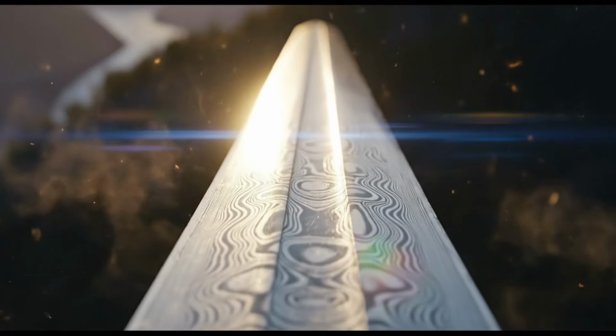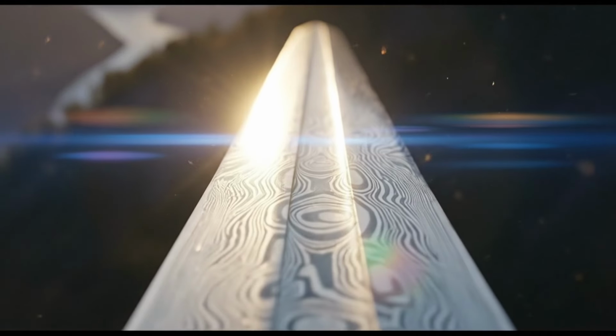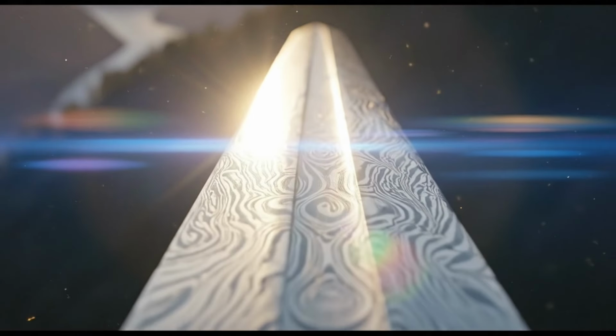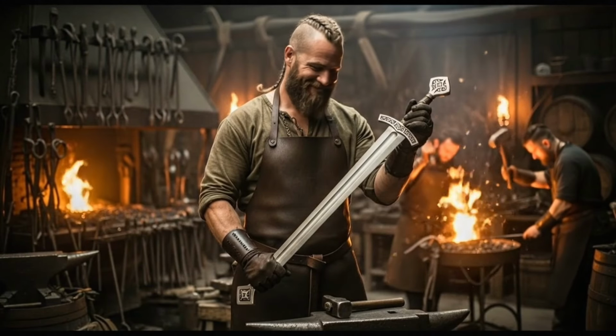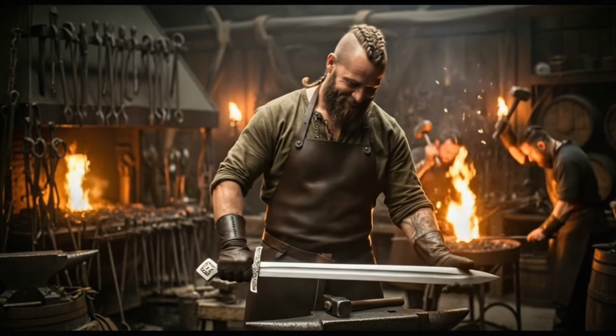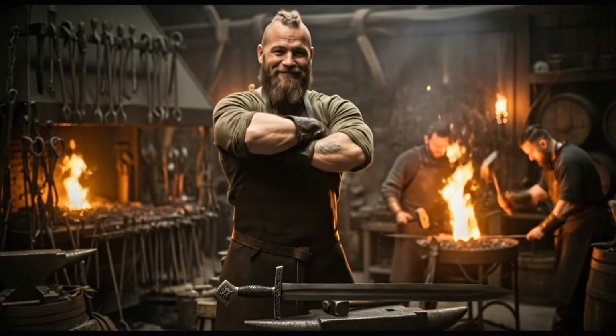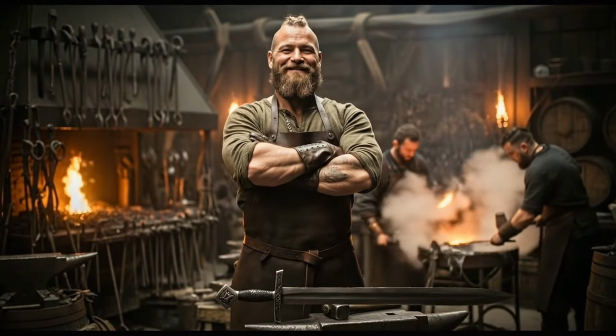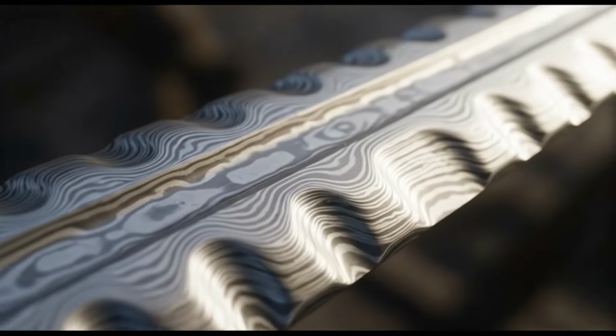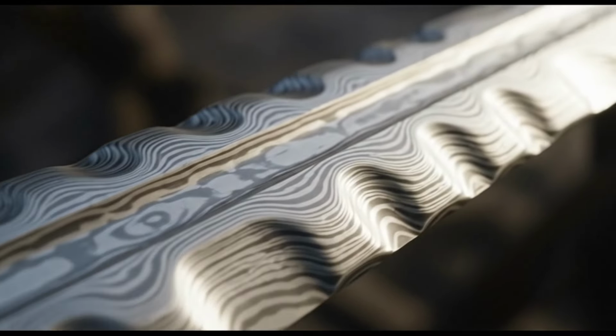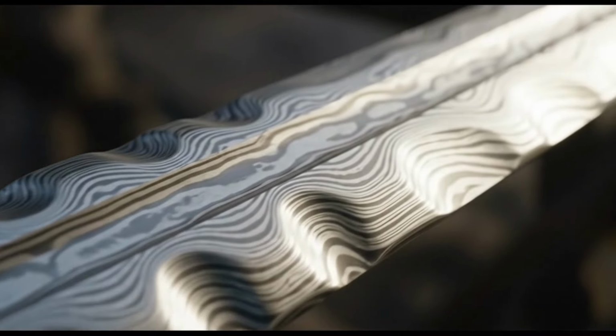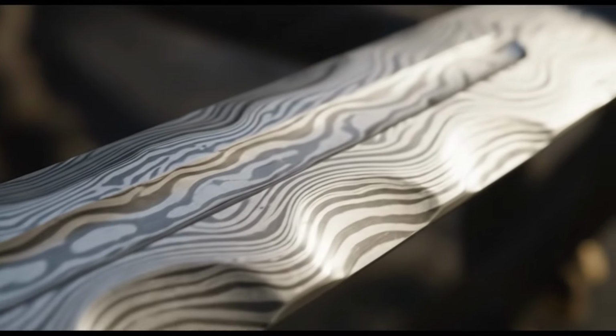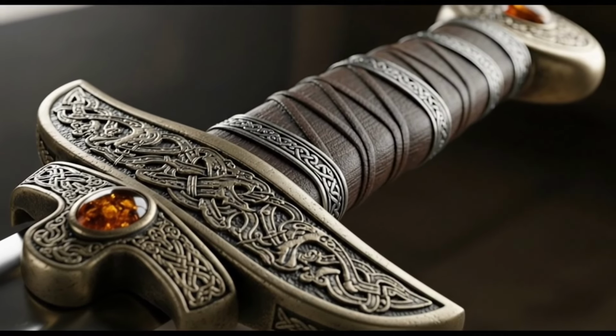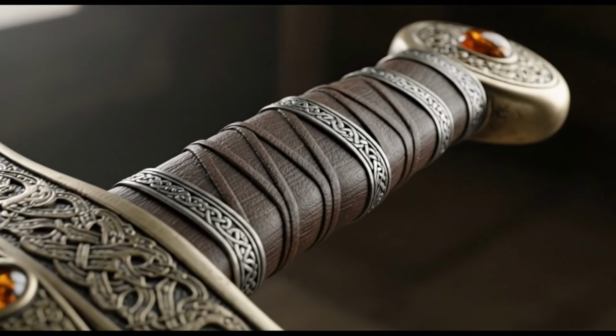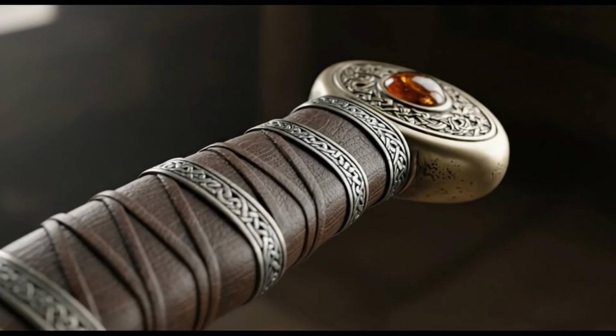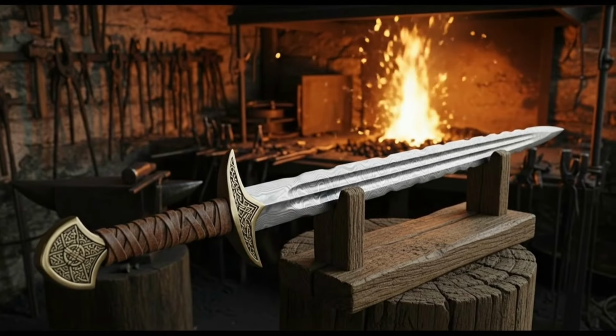After blades were completely forged and polished, the most critical and risky stage began: heat treatment. It was this stage that transformed steel pieces into real weapons. The slightest mistake at this stage would instantly destroy weeks of painstaking work. Heat treatment consisted of two main procedures: hardening and tempering. Hardening was necessary to make steel as hard as possible. To do this, blades were heated evenly to certain temperatures, which masters determined by heat color, usually cherry red color.